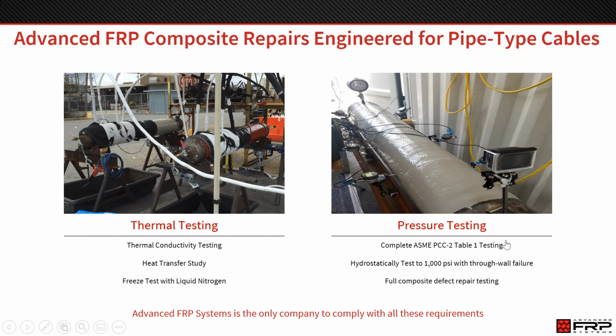When doing large sections of pipe type cables, there are pipe supports, temporary pipe supports in place. We ran into splice joints or hi-hats, existing barrels from previous repairs. Plus, defects are going to happen in composite repairs when you're doing long sections. So we fully pressure tested all these different potential issues that we were going to run into in the field, all up to 1,000 PSI with a through wall failure in the host pipe.